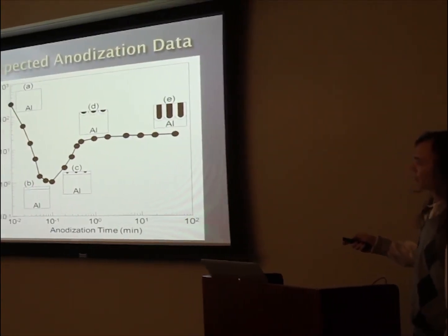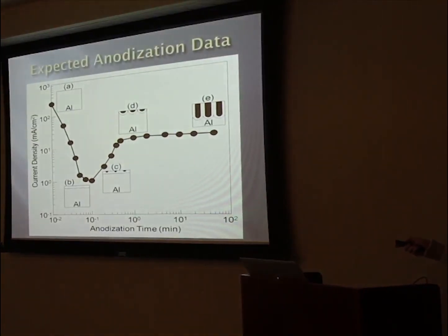So what do we expect when we take data from this? So initially you start, so this is going to be a graph of current density versus anodization time, but this current density is proportional to that voltage across the resistor I showed you before. So when you start, you are going to jump up in voltage, you're going to have pure aluminum at the top, and then as this oxide layer forms, it's going to become more resistant, so you're going to get less and less voltage across here, so you drop that current, Ohm's law. But then as these pores start to form, you get less resistance. It's going to build up more and more as these pores start to form deeper and deeper, and then as they get to a certain depth, it starts to plateau.